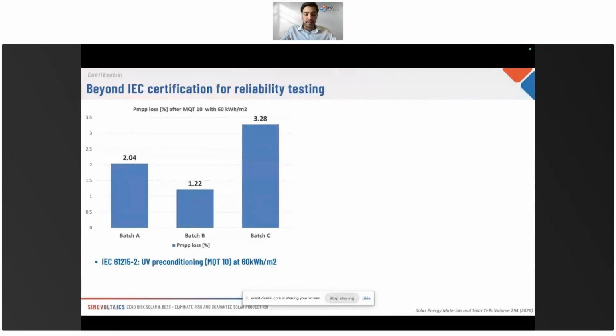Now, if we look at the data from our inspections and different lab reports, here we have 3 different batches of TOPCon modules that were tested following the current standard for UV-related degradation, which is this one. In this case, it was tested at this dose, which is 60 kilowatt hours per square meter. As we see in this specific case, only one batch was flagged as a failed test, not because of the standard, which is set at 5% degradation, but because the contract agreement between the client and the manufacturer was stricter, set at 3%. So it allowed us to detect this degradation early on.